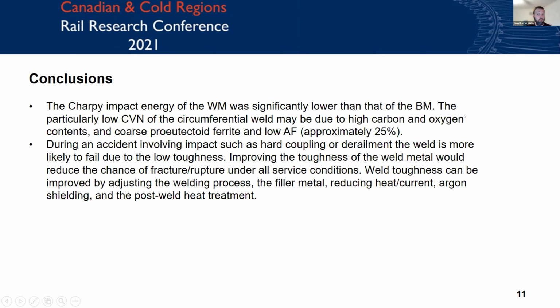Improving the toughness of the weld metal would reduce the chance of fracture rupture under all service conditions. Weld toughness can be improved by adjusting the welding parameters, the filler metal, or reducing the heat or current supplied to the weld, potentially adding or changing the shielding and the post-weld heat treatment.